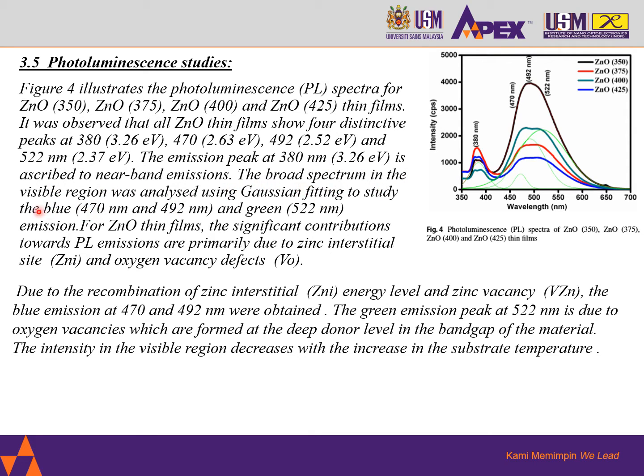The broad spectrum in the visible region was analyzed using Gaussian fitting to study the blue 470 nanometer and 492 nanometer and green 522 nanometer emission. For zinc oxide thin films, the significant contributions towards PL emissions are primarily due to the zinc interstitial site and oxygen vacancy defects. Due to the recombination of zinc interstitial energy level and zinc vacancy, the blue emissions at 470 and 492 nanometer were obtained. The green emission peak at 522 nanometer is due to oxygen vacancies which are formed at the deep donor level in the band gap of the material. The intensity in the visible region decreases with the increase in the substrate temperature.